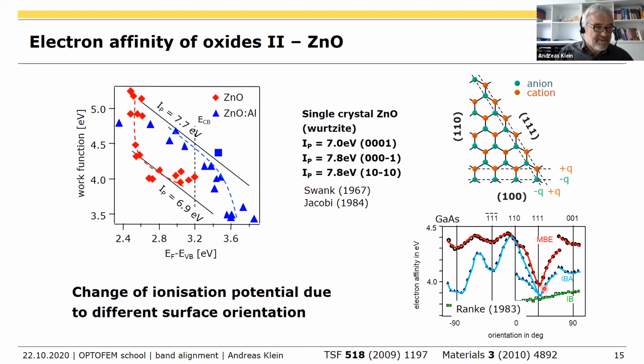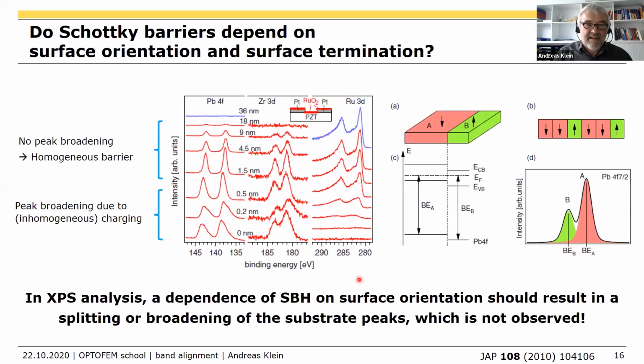Okay, so now which one do you want to take for predicting the Schottky barrier? You can take either 7.7 or 6.9. And typically, the Schottky barrier does not depend on the orientation and also not on the surface termination. So that's one example.